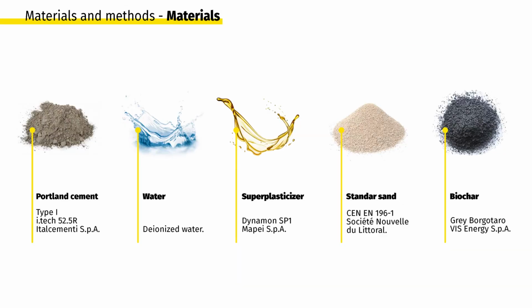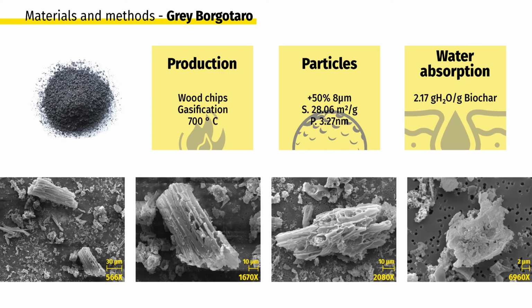Portland cement type 52.5R, deionized water, superplasticizer, standard sand, and biochar were the materials used in this work. In this work, Gray Borgotaro biochar was used, produced through gasification at 700 degrees Celsius, using wood chip as a raw material. Specifically, more than 50% of the particles have a dimension between 0 and 8 micrometers, with a surface area of 28 square meters per gram and an average pore of 3.27 nanometers.